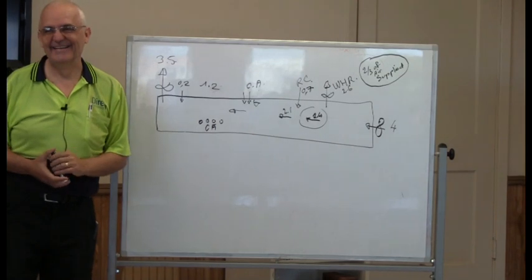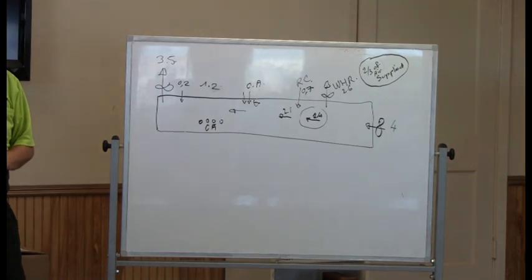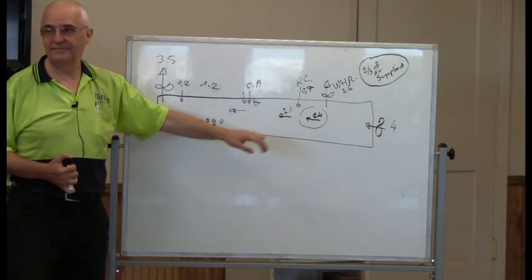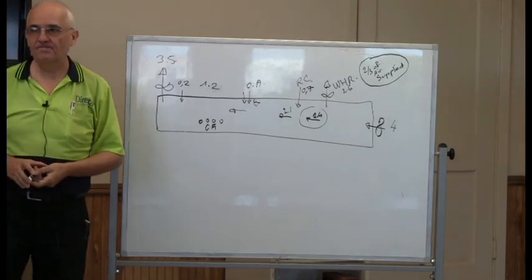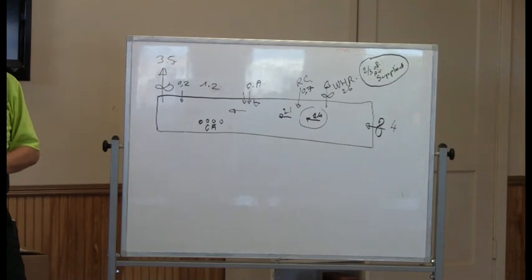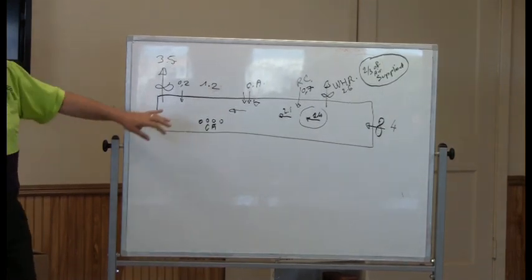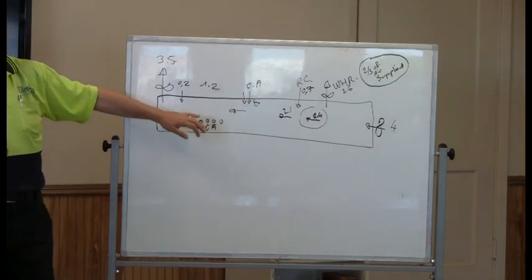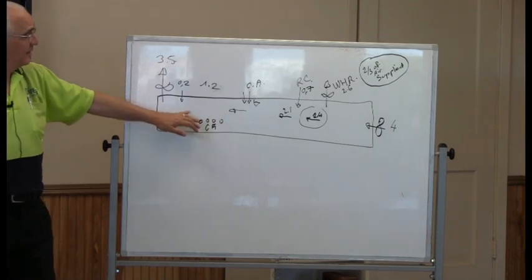I liked when you described it that way. You want to use the energy in the tunnel because it's there, and the temperature's 1500 degrees. Yes, 1600 degrees. If you don't use that 1600 degree air, you're going to use ambient air from outside through the burner. Exactly. You're much better off using the 1500 you've got in that air already, plus add to it with burners. Exactly. Plus, you know, preheat a lot of time.